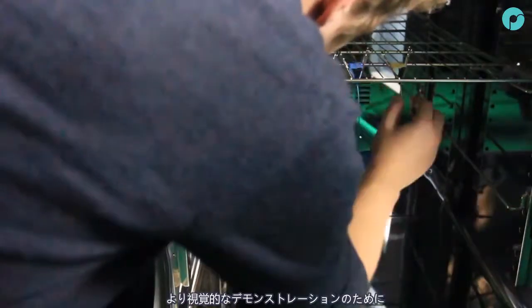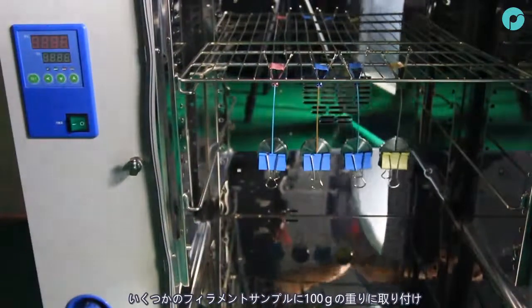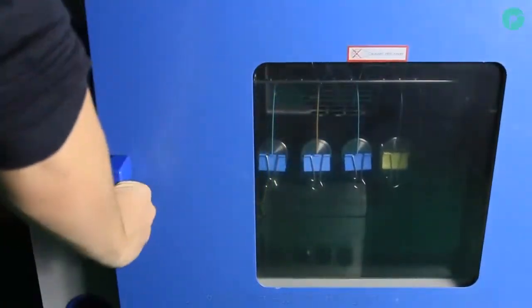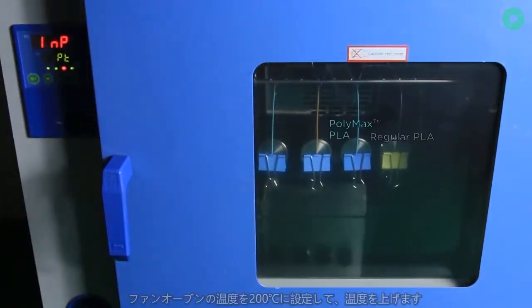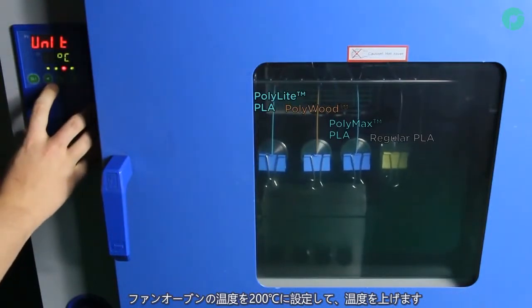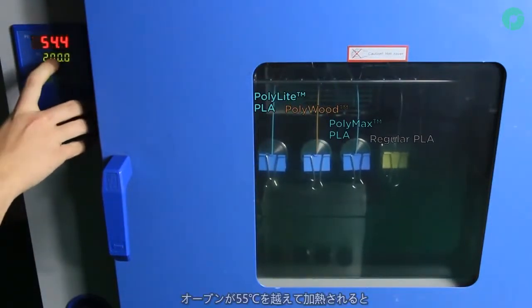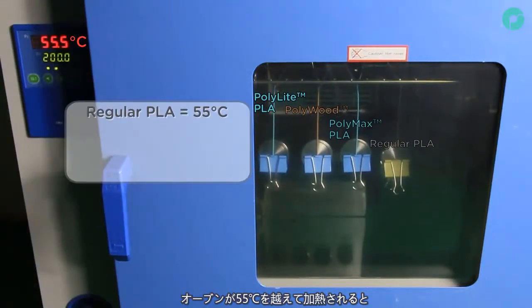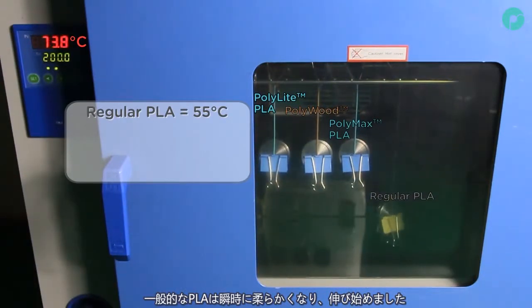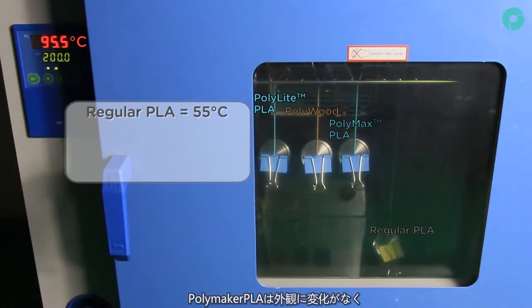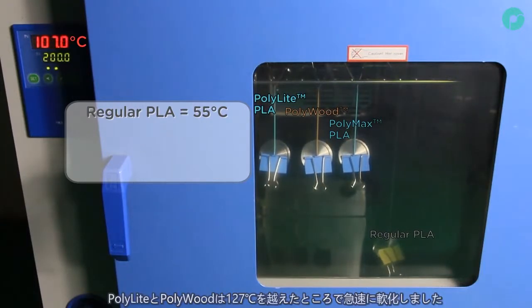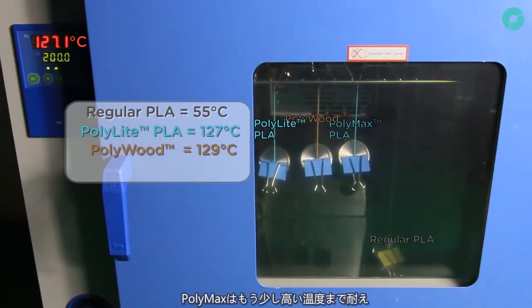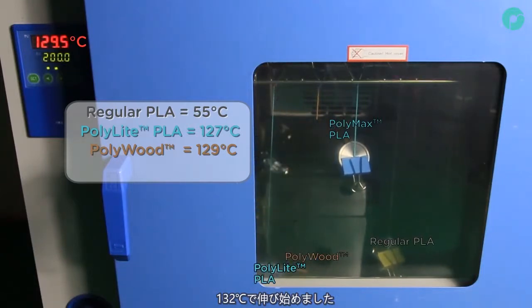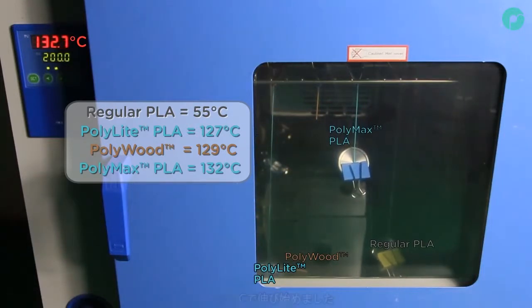To show a more visual representation, we have attached some filament samples to the 100-gram weights and placed them in a digital fan oven. We set the temperature to 200 degrees centigrade and allow the temperature to increase. Almost instantly, the regular PLA starts to soften and stretch as the oven heats up past 55 degrees. The Polymaker PLA filaments show no change until we reach 127 degrees, when the Polylite and Polywood filaments rapidly soften. The Polymax withstands a little more temperature, not stretching until we reach 132 degrees centigrade.